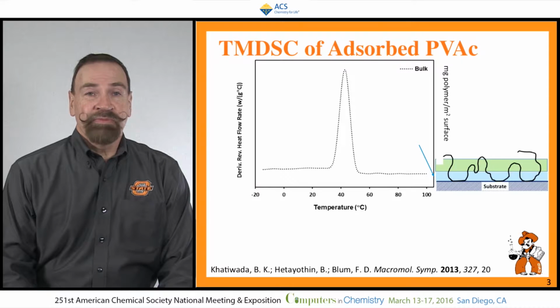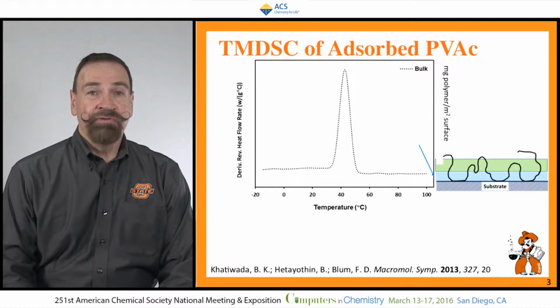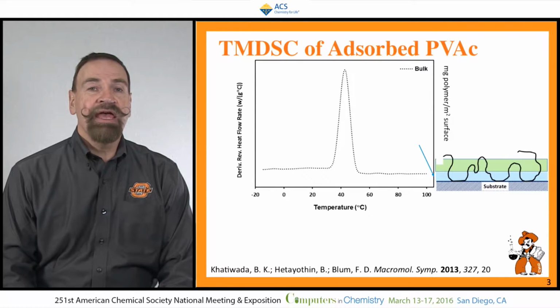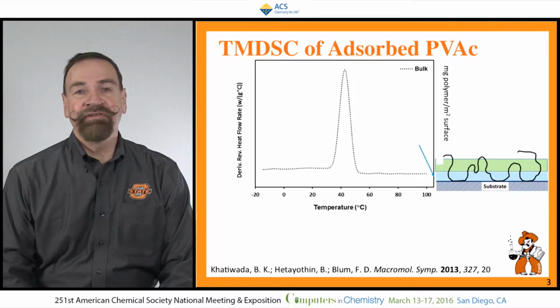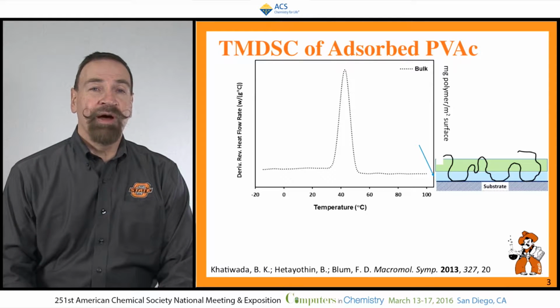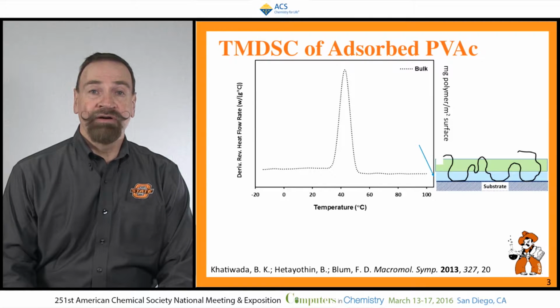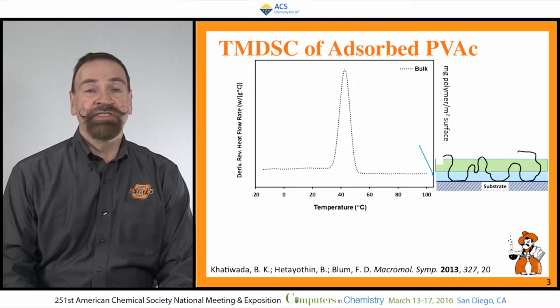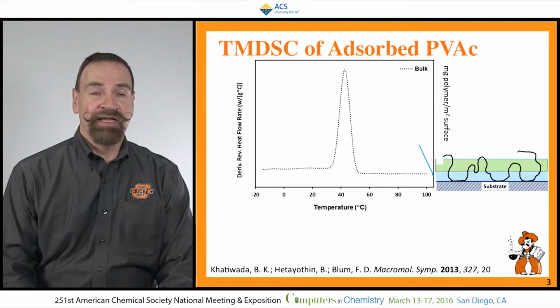If we look at this polymer, we can characterize it through differential scanning calorimetry. This turns out to be temperature modulated differential scanning calorimetry, and on the slide is the derivative of the heat flow curve for bulk polyvinyl acetate. What we see in the curve is that a glass transition is apparent, and it is moderately narrow, about 10 degrees wide, and occurs at the bulk glass transition temperature for polyvinyl acetate.